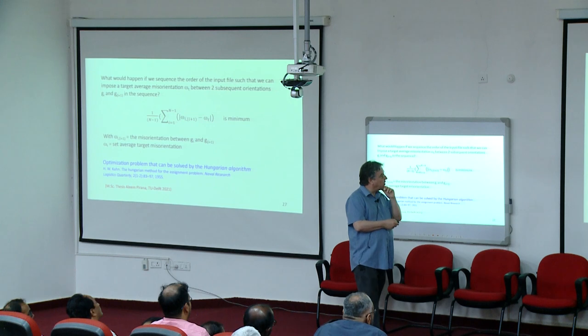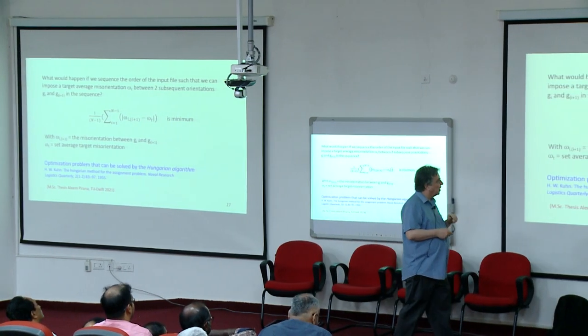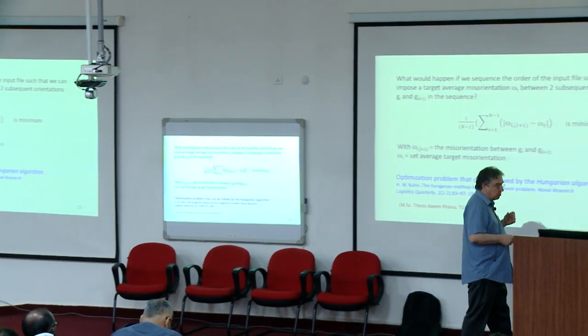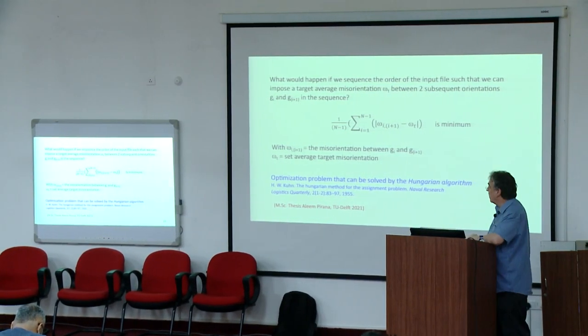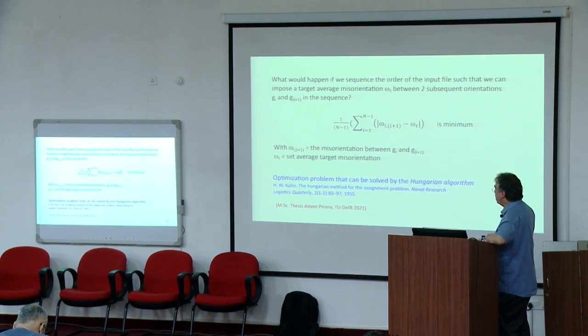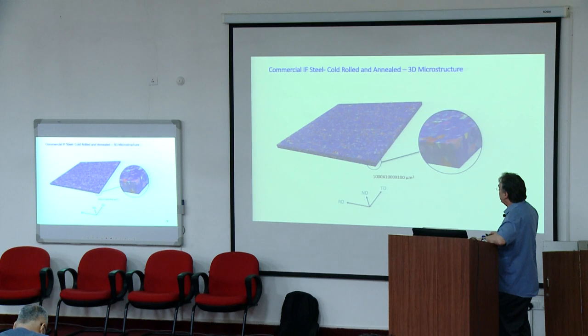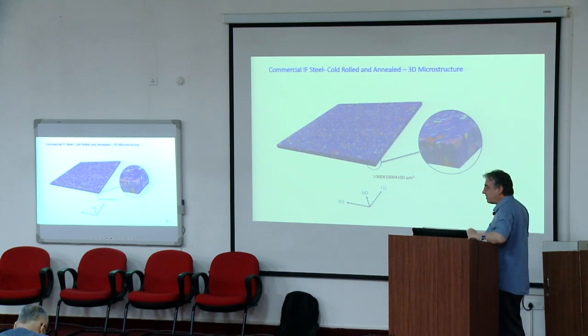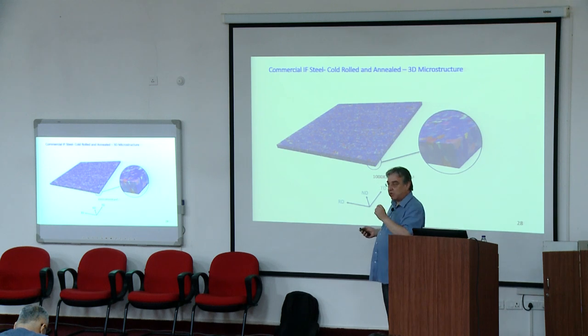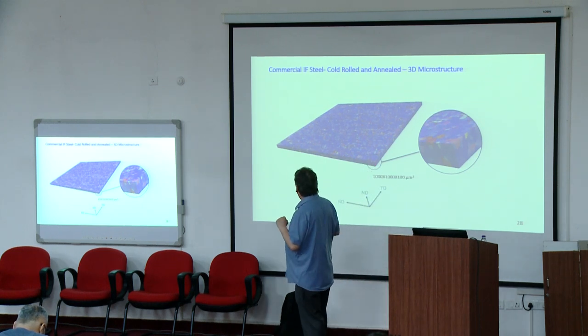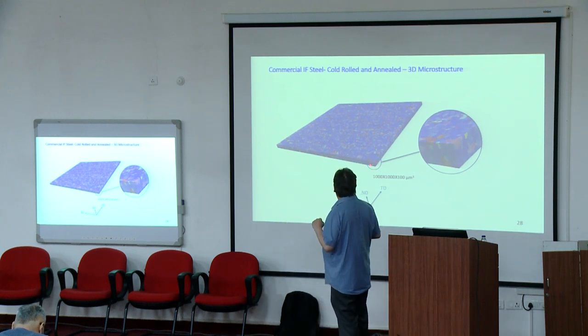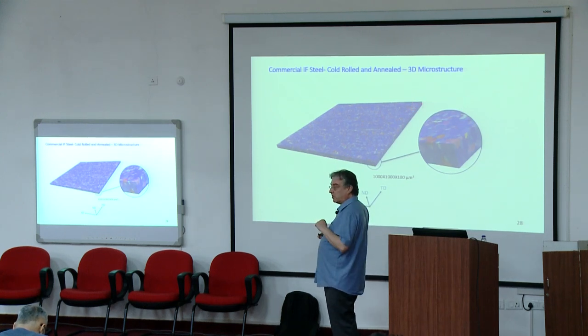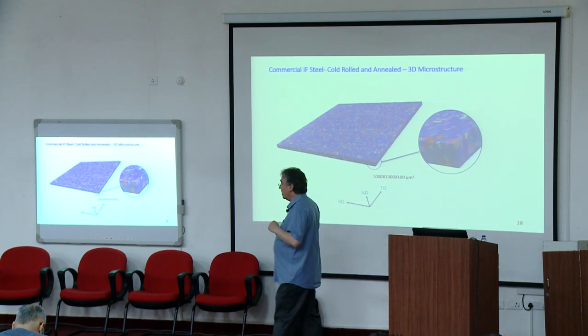So we also tried some other things to better pair the crystal orientations. But in the end, we proved that, in fact, it was not that sensitive. We even tried to extract the pairing from the real 3D microstructure. If you measure a microstructure in 3D, and it's a real huge chunk of material, this is an IF steel, which we measured in 3D by EBSD. So this is 1 millimeter by 1 millimeter by 100 micrometer. Such one measurement takes easily 3 weeks.